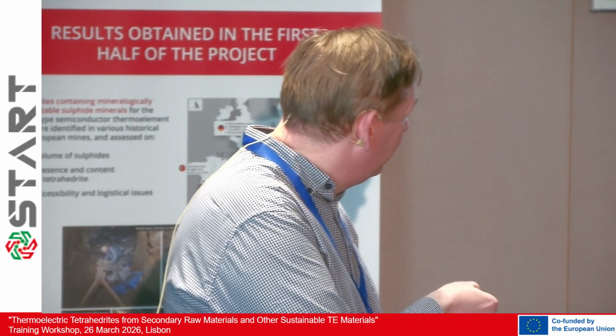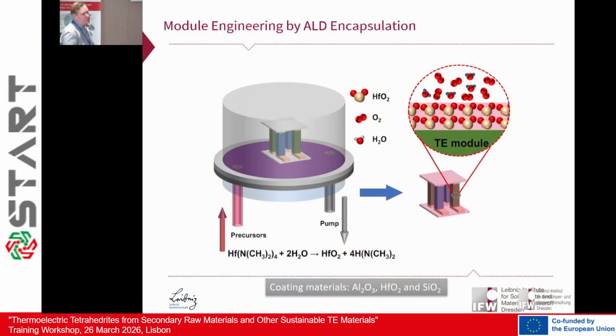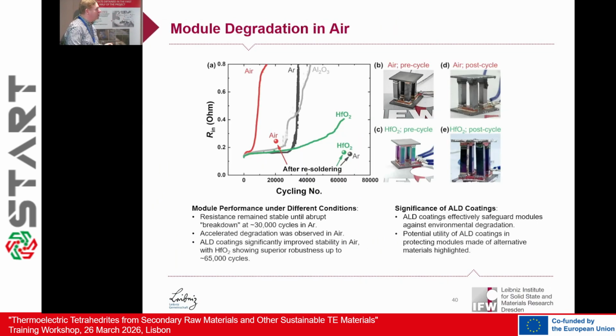The most ideal are now silicon oxide and hafnium oxide. These two materials we now use for the coating of these modules, and we typically coat about 200 nanometers of oxide material. This gives you an impression of how the assembled module looks when we are not doing any cycling. This is a simple module with a 2x2 configuration.